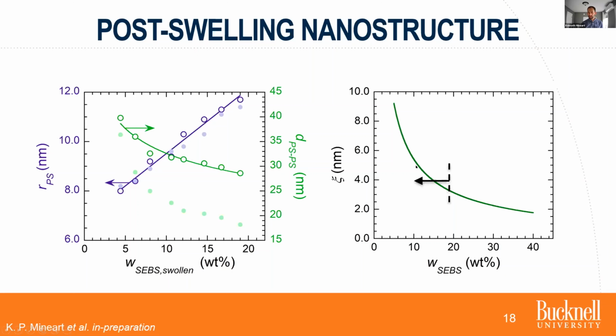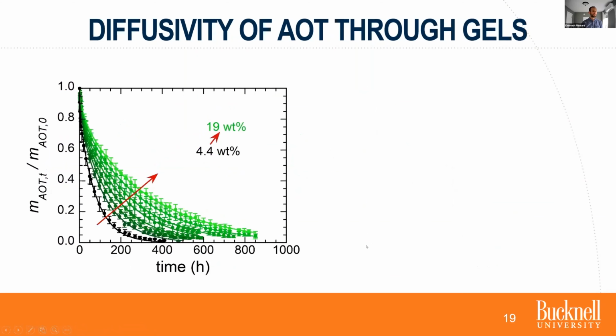And so we're just examining a different part of the curve in terms of our structure. So now, like I said, we repeat the same transport experiments. Not a lot experimentally changes except we're now handling pre-swollen gels. And so the triblock copolymer concentration is quite a bit lower, but we still get very similar release curves, and they still correspond to faster release for lower triblock concentration and slower release for higher triblock concentration, except now we can model them using Fick's second law with appropriate boundary and initial conditions.